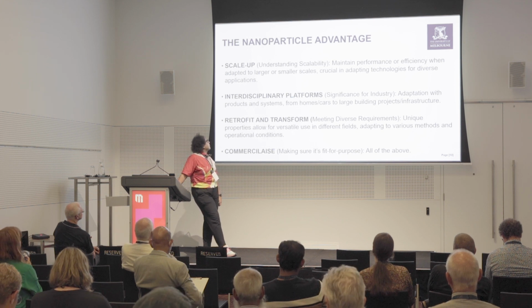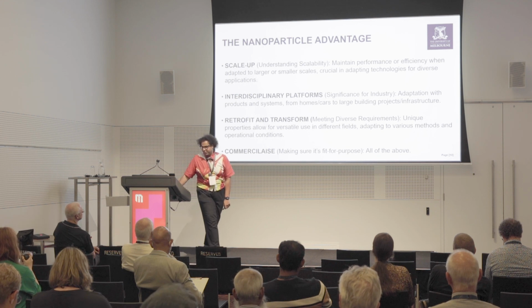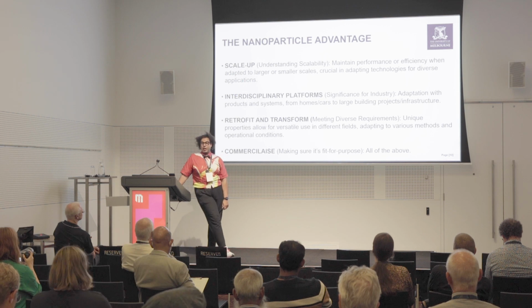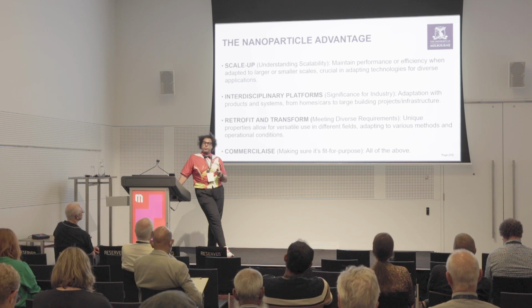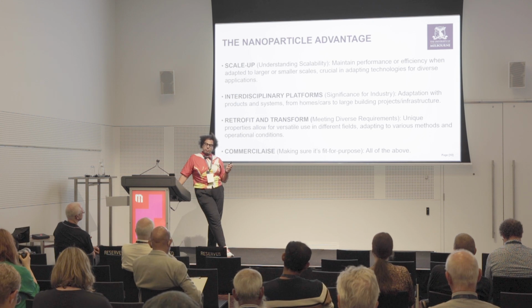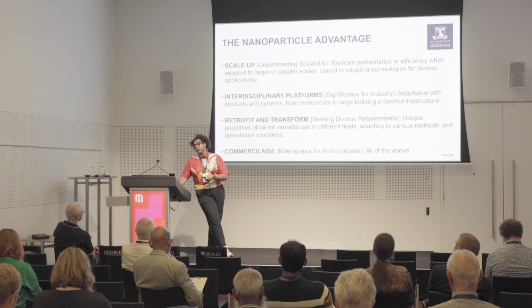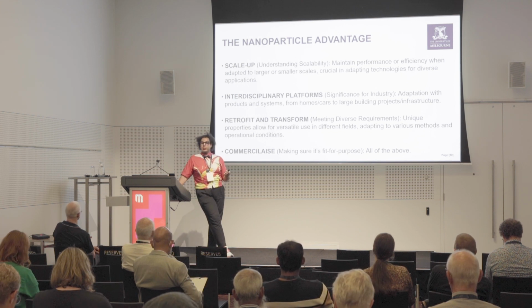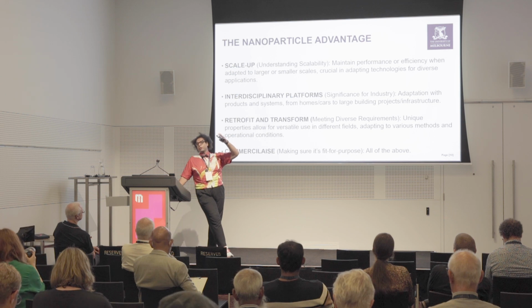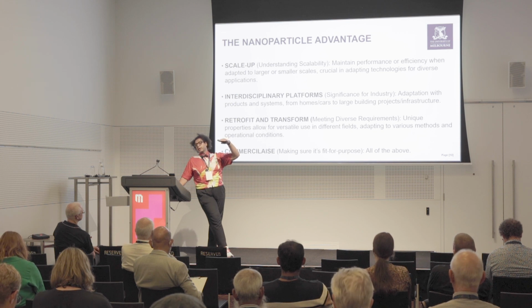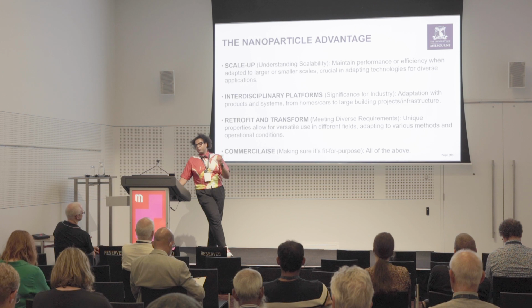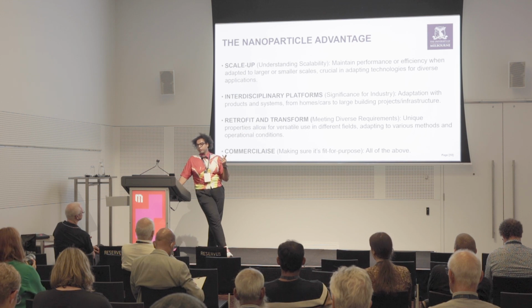It is important to have something that is scalable and repeatable, because I've made vanadium oxide in all the ways that you can make it, and I settled on this one because of the versatility of how you can make it, how much you can make of it, and how you can apply it. Again, if you're talking about a heterostructure, every material in that heterostructure has its own synthesis recipe of how you make it. So if you have two materials that are incompatible entirely in how you make them, you can't make that device, even though scientifically they would gel so well together. In practice, when you put the second layer on top, your device is cooked, because you've compromised the initial layer.